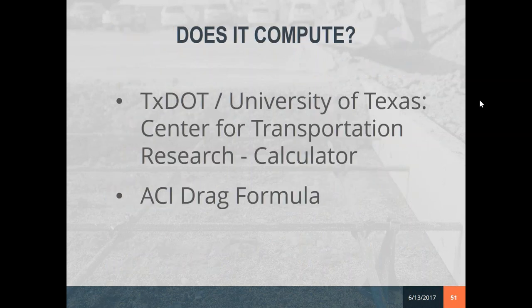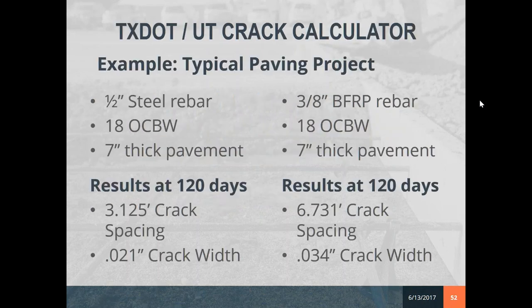The University of Texas and TxDOT got together, and there's an ACI formula that could be used to determine crack spacing in continuously reinforced pavements. They came up with a little crack calculator that you can get a hold of, and you basically put your section properties into the formula. So taking a half inch steel rebar at 18 inches on center, 7 inch thick, as you can see here, you would end up with crack spacing about every 3 feet at the end of 120 days. With the same configuration with FRPs, you end up with crack spacing about every 7 feet. It's a little wider crack due to the lower tensile modulus, not as stiff, but it basically allows the concrete to breathe a little bit and move around, allowing less cracking within your infrastructure.